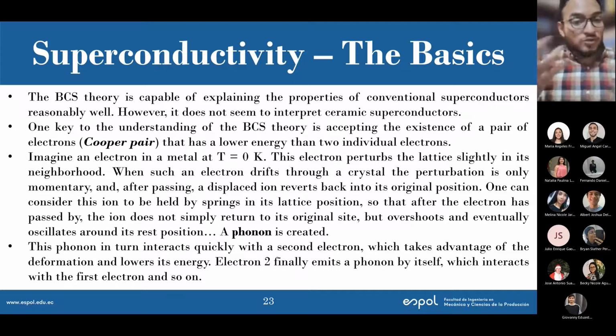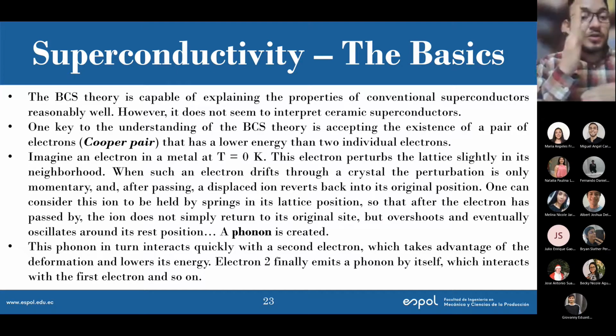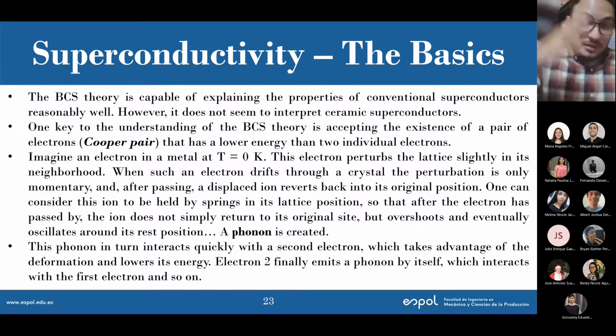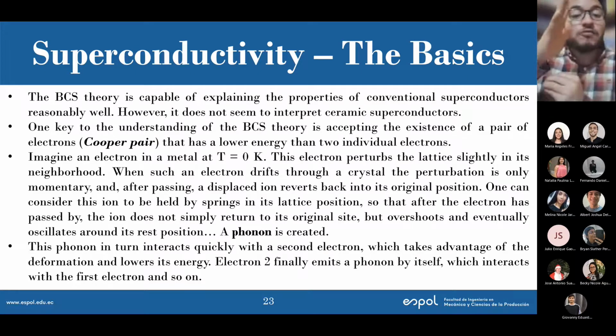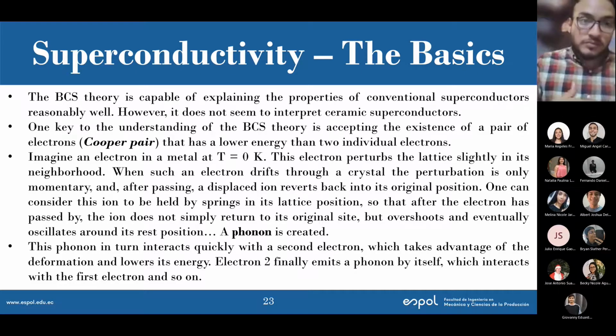So just to repeat, one electron perturbs the crystal, the ions that got perturbed go back to their original position but start oscillating. That is a phonon. Another electron comes, interacts with that phonon, takes advantage of that deformation, and lowers its own energy. Once it lowers its energy, it can emit another phonon, and that phonon will interact with electron one, and therefore we have two electrons paired, interacting back and forth with the phonons that they created. Therefore I have a Cooper pair.